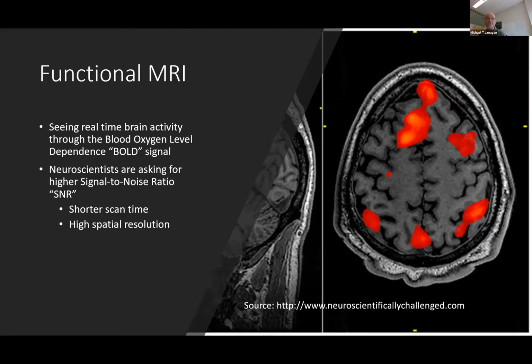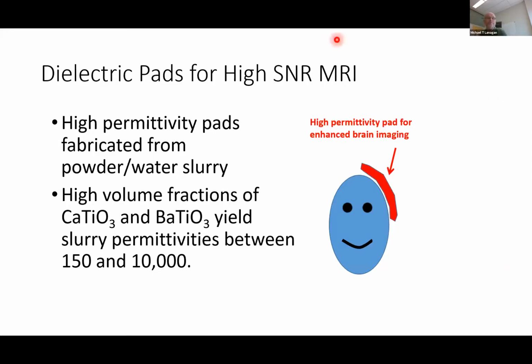So how do we do this? So here, I propose that we use these dielectric pads for high signal to noise ratio magnetic resonance imaging. And just this little cartoon, I don't show the coil here, but what we're essentially doing is we're putting a dielectric pad on top of the head. And here we can make this pad a slurry of water and high permittivity powder, or we can actually make it a monolithic pad of a ceramic material that basically has a certain permittivity.